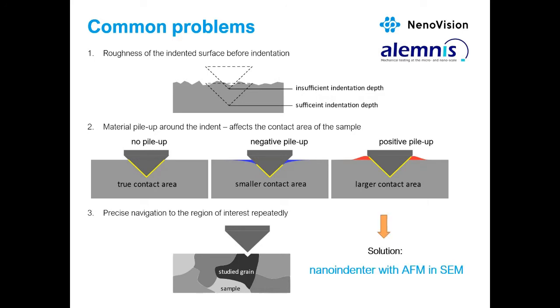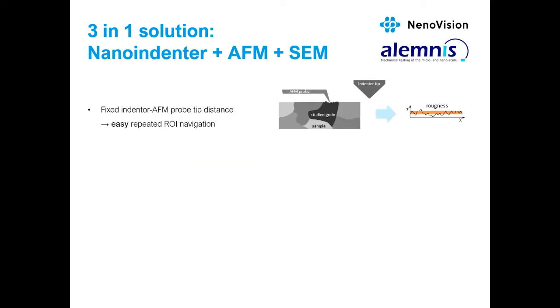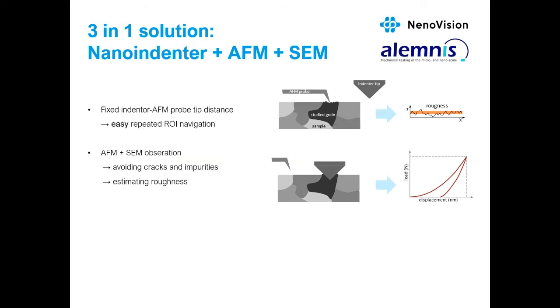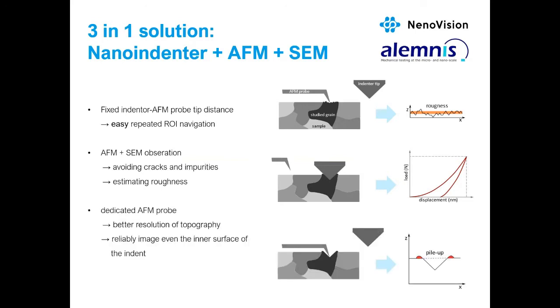The solution overcoming these problems is the 3-in-1 Nanoindenter with AFM in SEM. The optimized procedure is to localize the area of interest, measure the roughness by AFM, avoiding any cracks or impurities using the SEM observation. Then we make the nanoindentation tests, and using high-resolution AFM, we measure the indents for the real depth and pile-up effects, etc.